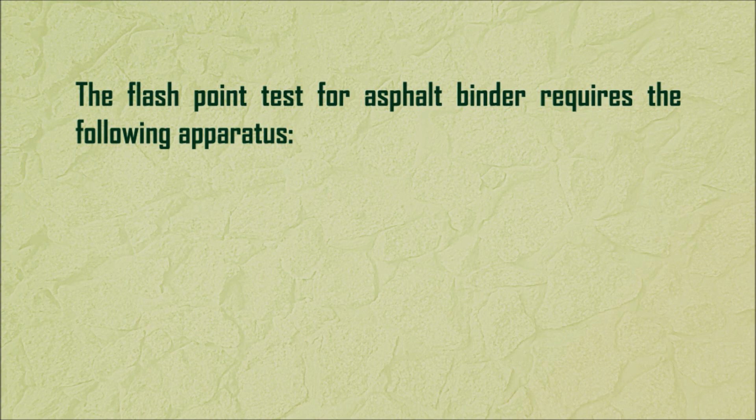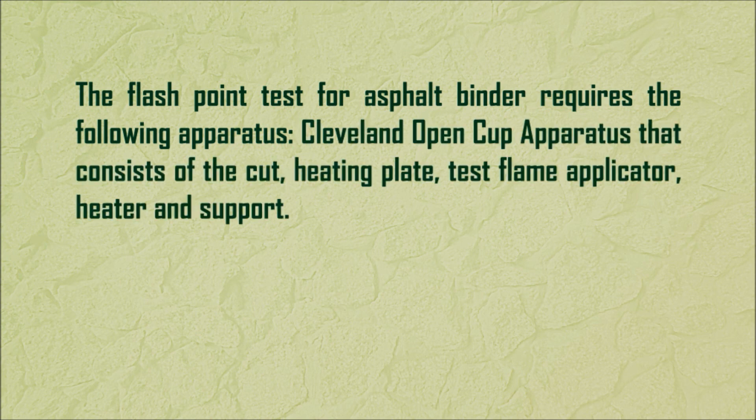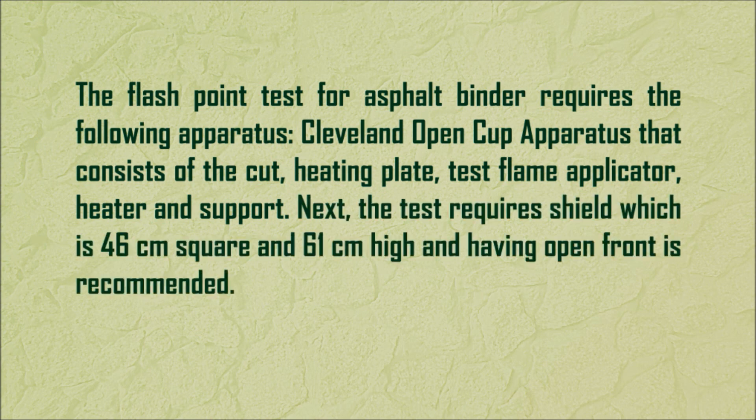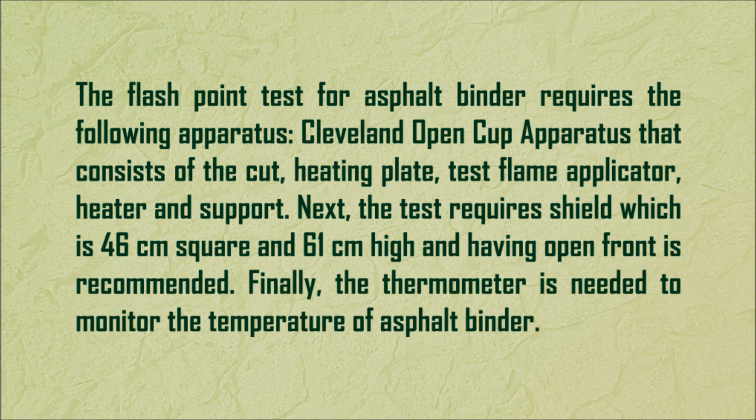The flashpoint test for asphalt binder requires the following apparatus: the Cleveland Open Cup Apparatus, which consists of the cup, heating plate, test flame applicator, heater, and support. The test also requires a shield that is 46 cm square and 61 cm high with an open front. Finally, a thermometer is needed to monitor the temperature of the asphalt binder.